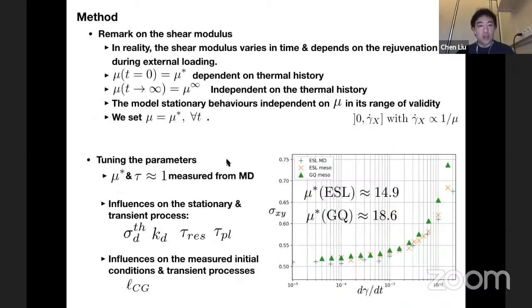So just a remark before I proceed. In principle, the shear modulus should also depend on time, because at time zero the system is just after quench. The shear modulus should be that of the system just after quench, so it's a value that depends on the thermal history, and after the system is driven, at the long time limit, the system enters a stationary state. It should converge to a value that is independent of the thermal history.